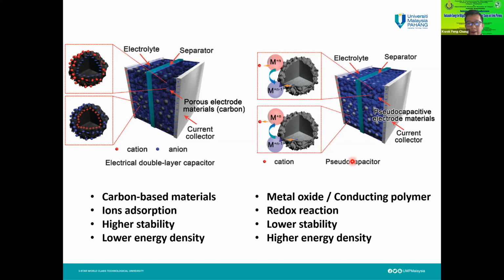If you look at the right-hand side, we have the pseudocapacitor, whereby the material that we use is a metal oxide or a conducting polymer. The principle for this energy storage is based on the redox reaction. It's based on the changing of the oxidation state of your metal oxide or conducting polymer. So that's why it will generate changes in the charges, and you can store the charge in the material. Because it involves the redox reaction and the changing of the oxidation state, in the end it has a very low stability, but the benefit is that it has a very high energy density. So that's the material that I'm going to talk about in today's topic.